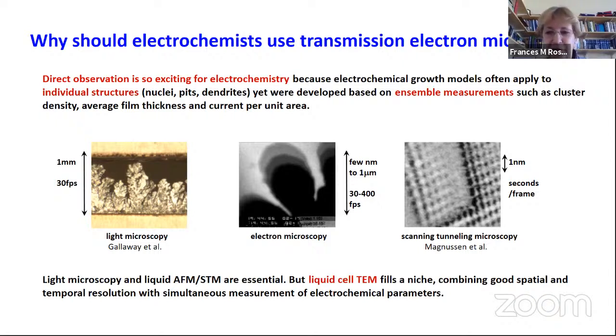What is the final cluster density in nuclei per square nanometer? What's the average film thickness? What's the average current density in the system? But fundamentally, these growth models are applicable to individual structures like nuclei, pits or dendrites. And so we need a way of linking the individual objects to the ensemble measurements that create them.